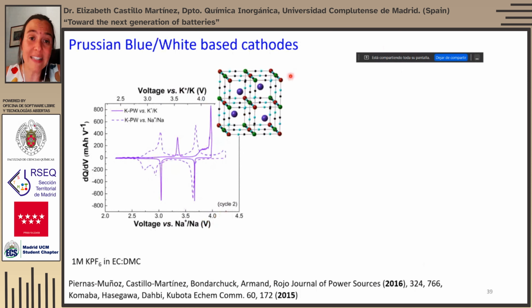For potassium-ion batteries, the Prussian blue materials are the preferred cathodes because their tunnel size perfectly matches the size of the solvated potassium ions. And you can see that the voltage is quite higher than that. The voltage of insertion of potassium ions is higher than the voltage of insertion of sodium ions in the same structure type.